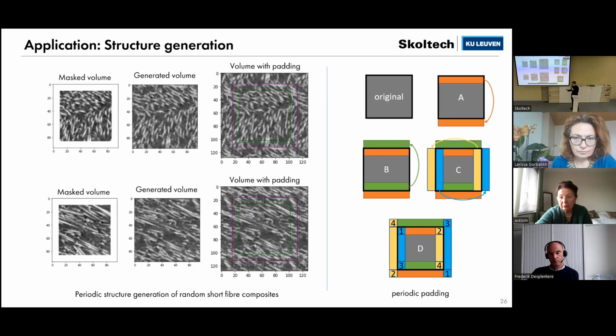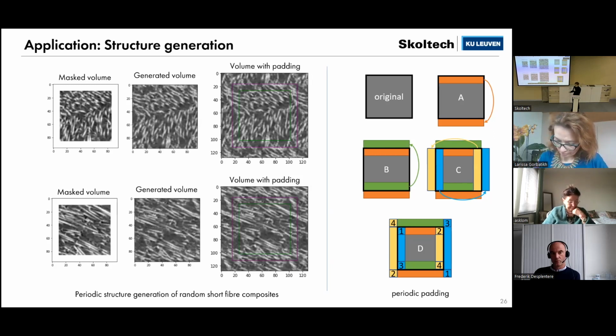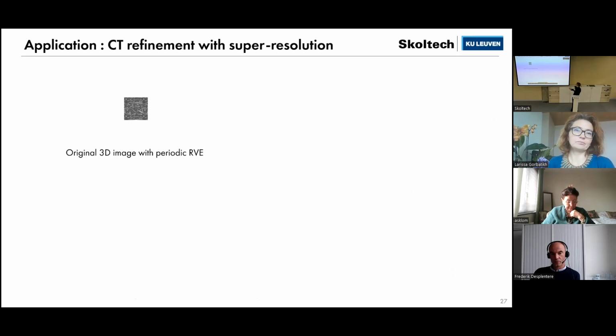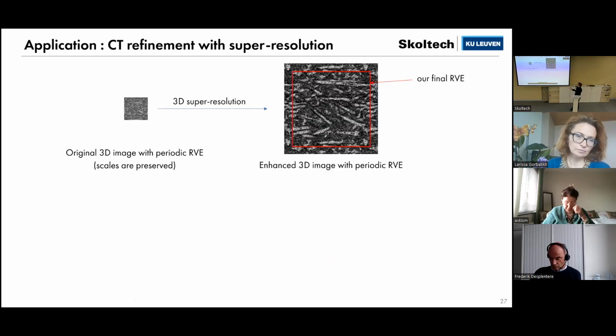So it's periodic. But if we compare periodicity pixel by pixel, we haven't achieved perfect periodicity. It was increased from 50% periodicity to approximately 90% periodicity. Also, we were able to create only small periodic representative volume elements because of hardware limitations, but using a super resolution algorithm, we were able to increase the image size and later analyze it.